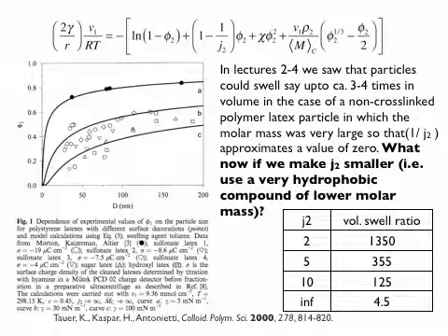which effectively means that if I have a little bit of low molecular weight, very hydrophobic material, I can retard Ostwald ripening. So before I thought that, okay, I have droplets of MMA or droplets of styrene, and it's game over because after 50 minutes, you know, it's completely ripened.